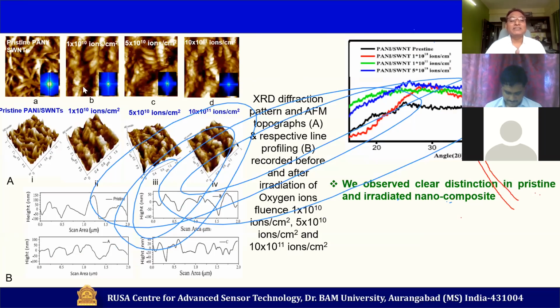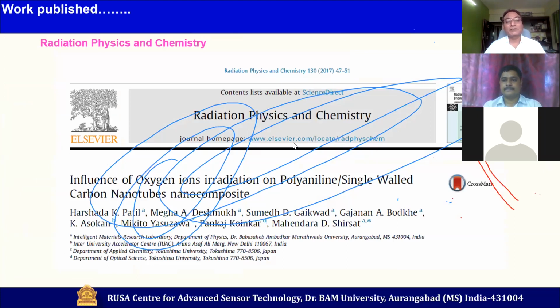You can see if we increase the degree of fluences, there is an increase in roughness of the film, the nanostructure, and this is what we were expecting. You can see through this height profile also that there has been a significant increase in roughness, and similarly from XRD also we got a significant distinction. And this work was published in Radiation Physics and Chemistry.